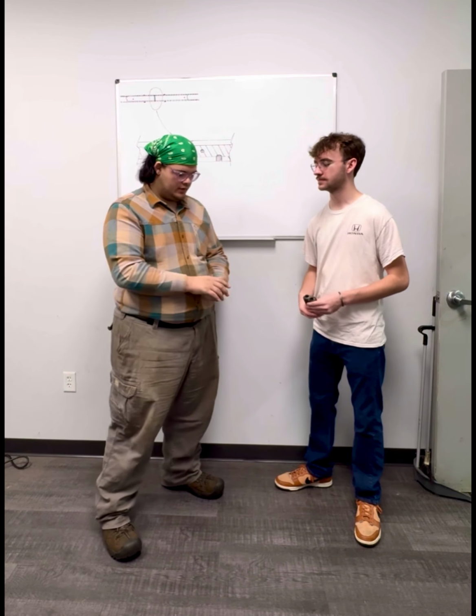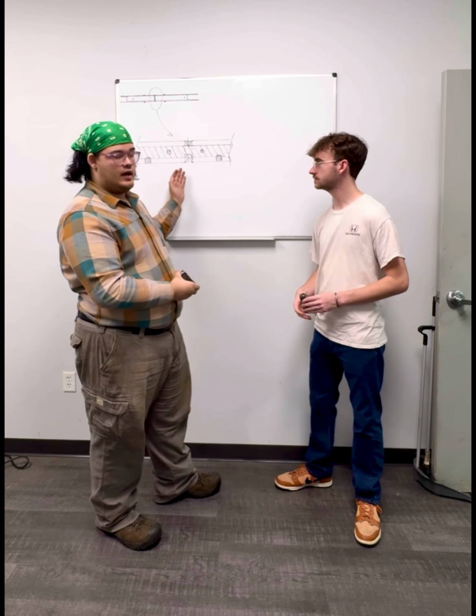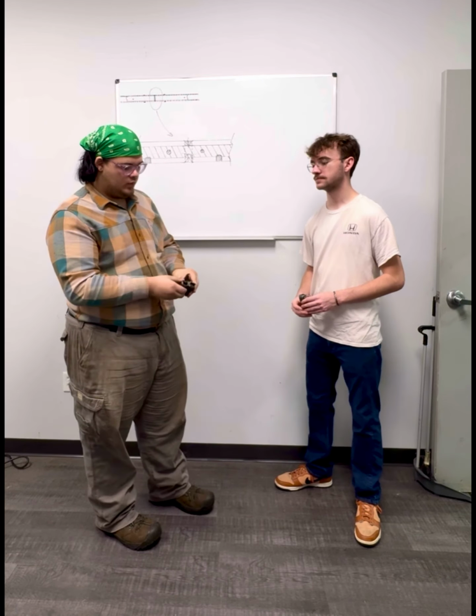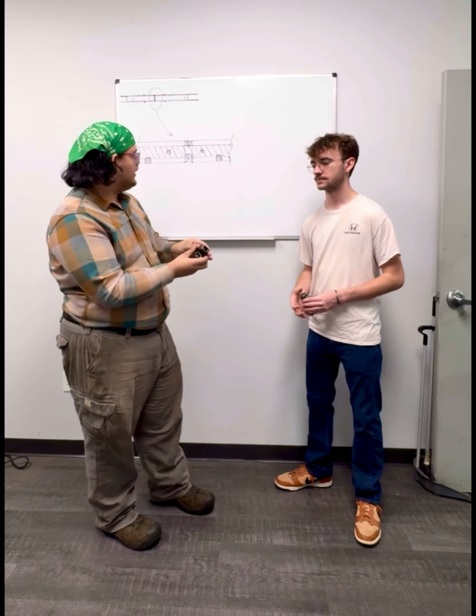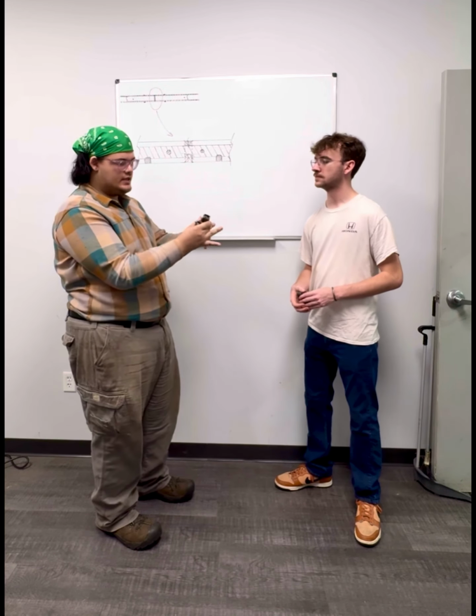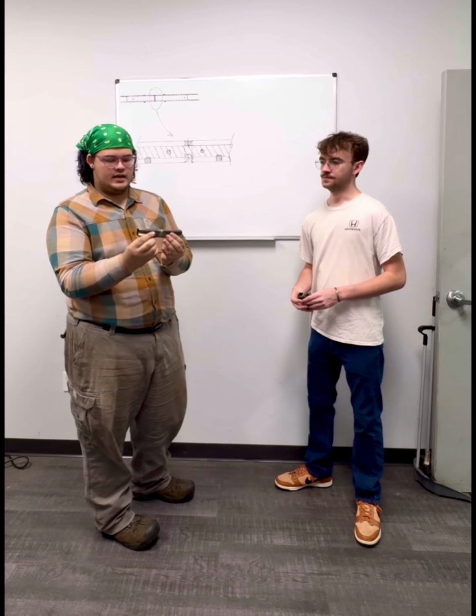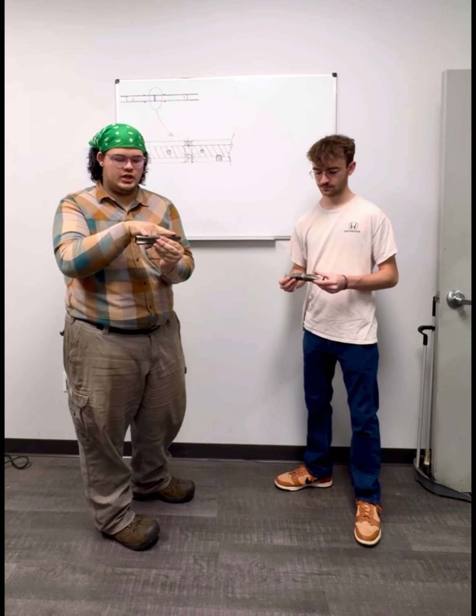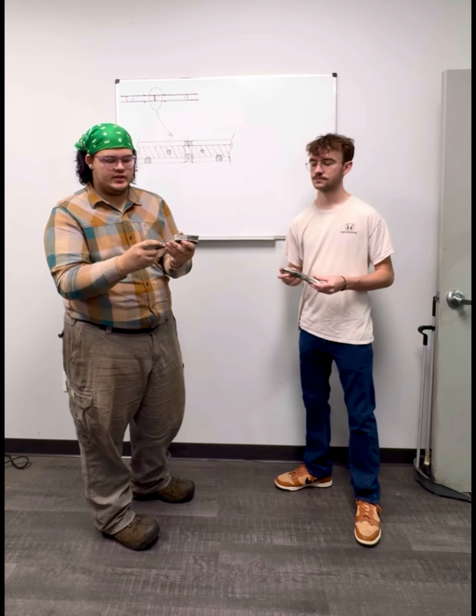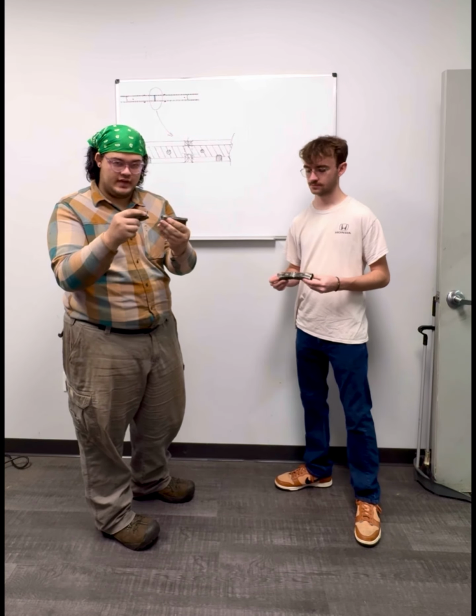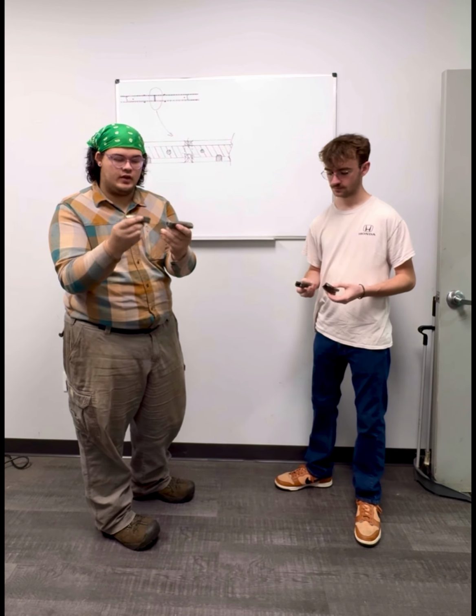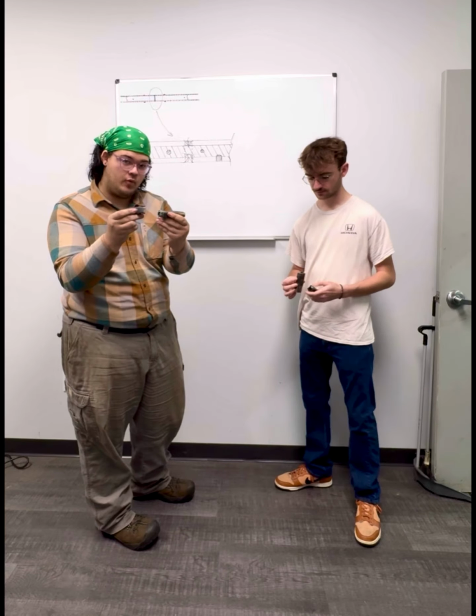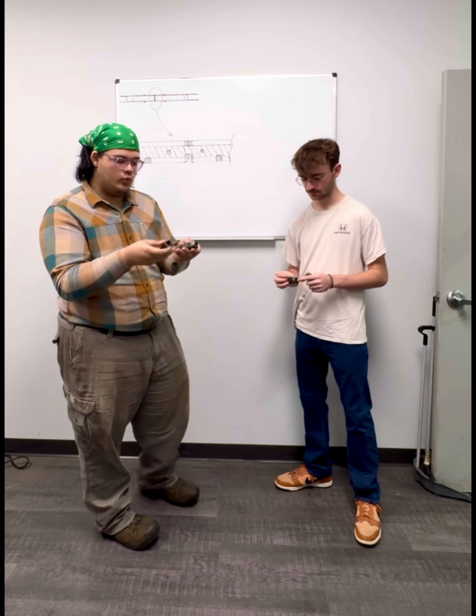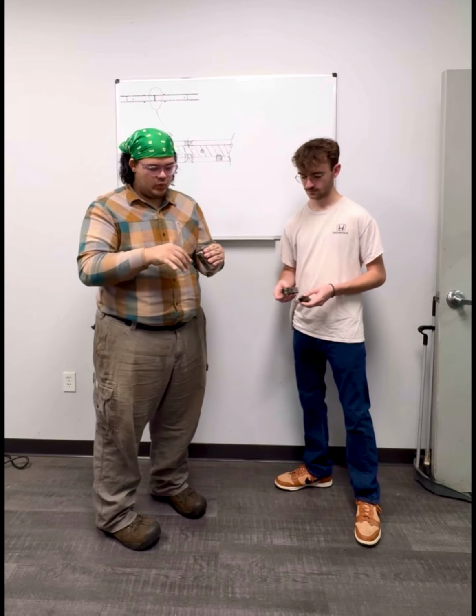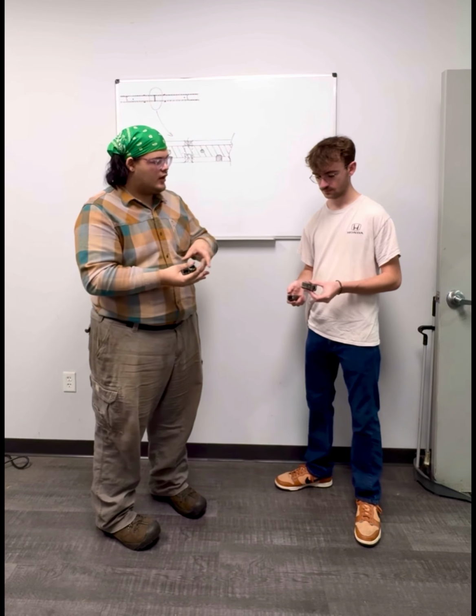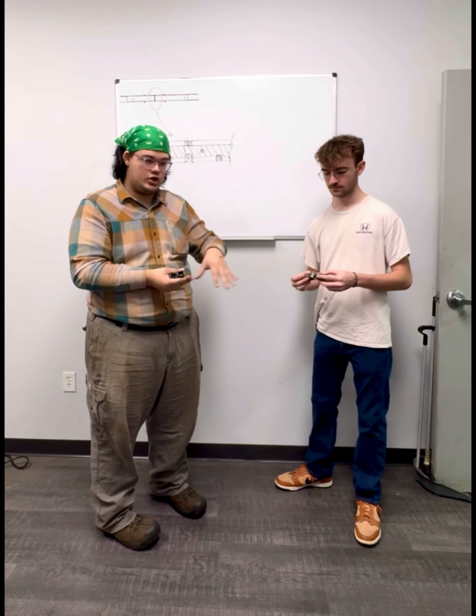So in the mock-up of the original chassis build, we took the exterior tubing and inner tubing, took the weld joint area and just condensed it, made a short mock-up about 6.5 inches long in total length with a 4-inch inner tube, and the spot welds placed roughly on 2 different faces, 1/2 inch away from the weld joint, and then on the other 2 faces, about 1.5 inches away from the weld joint. On one of these, we achieved full penetration to the inner tube, and on the other one, we only penetrated the exterior tube.